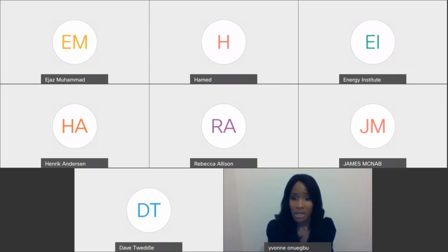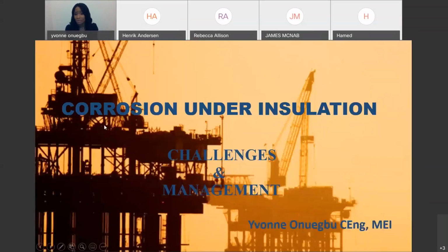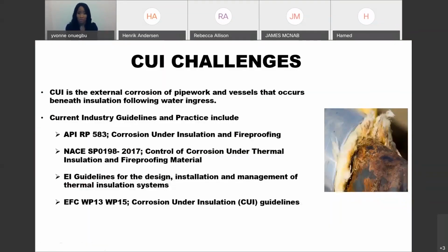So we keep talking about CUI challenges. Why does CUI present so many challenges? For me, it's because we're dealing with a lot of factors or parameters. We're dealing with inspection, temperature, moisture, contaminants, costs, maintenance requirements. So for example, if we pick on temperature, CUI occurs at a wide range of temperatures. If we are looking at carbon steel, we can get CUI from temperatures of maybe -4 degrees centigrade up to 175 degrees centigrade, although the highest probability would be at temperatures of around 30 to 120.